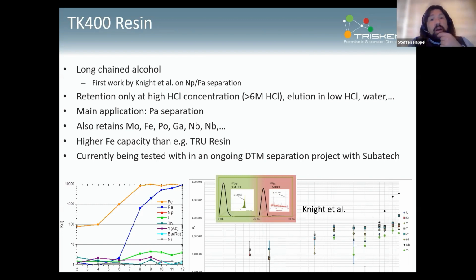You need to work at very high HCl concentrations, and even then, there's only a very limited number of elements that are actually extracted. So protactinium is certainly the main application. There are a couple of other elements like molybdenum, iron, polonium, gallium, niobium that are also retained. So protactinium is a bit the standard application. We started looking into using it for iron separation, as the capacity is about a factor of 4 or 5 higher than for the TRU resin. So that might be quite helpful, especially for somewhat more iron-rich samples.